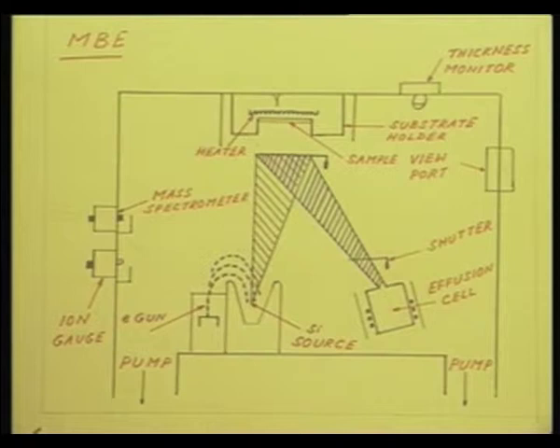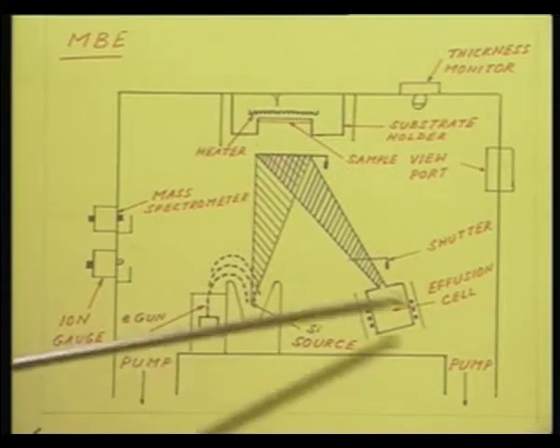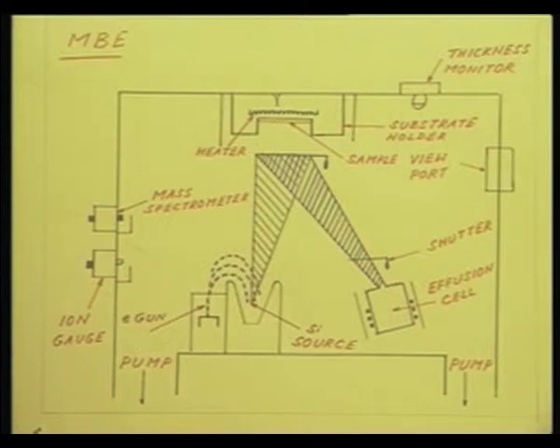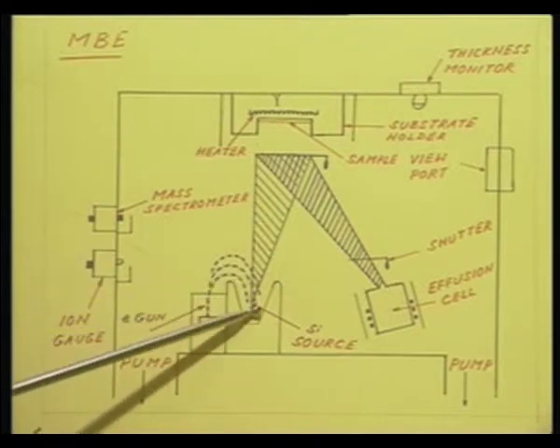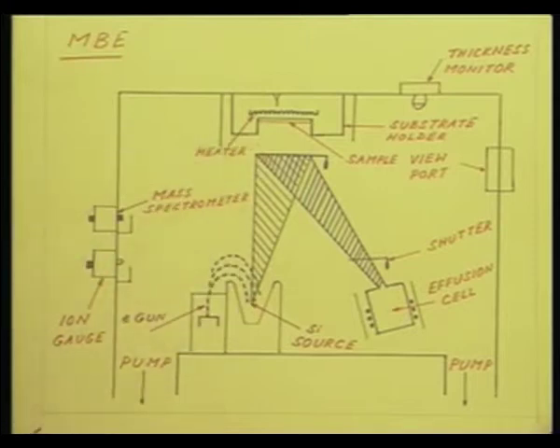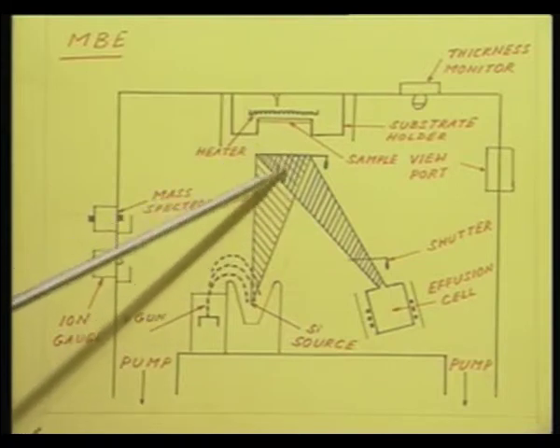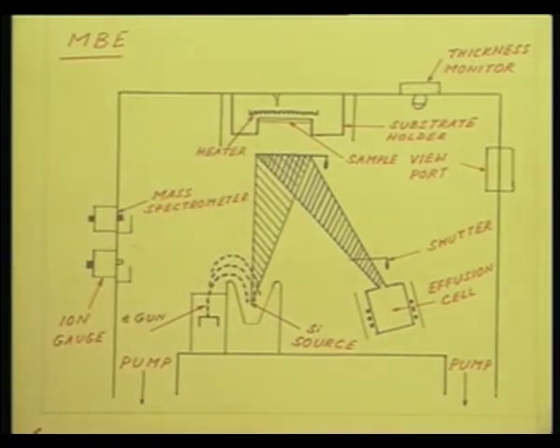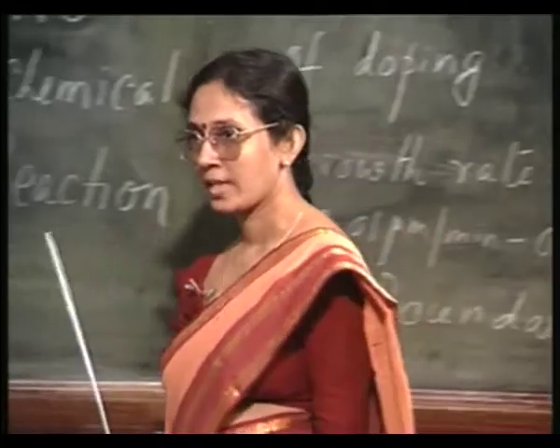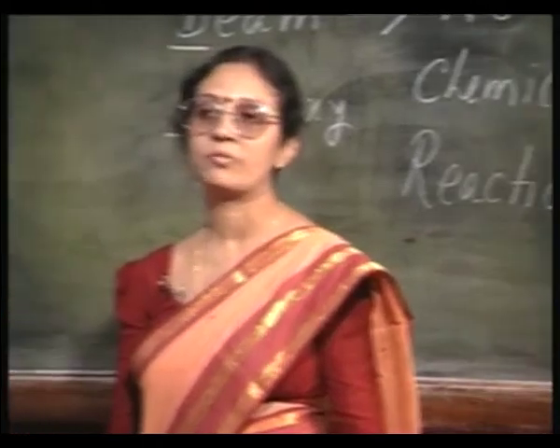So, essentially what is done is this: you pump down the system to the required vacuum level, and then you switch on the electron gun, the evaporated cone of silicon comes here. If you want to incorporate dopant, you heat the effusion cell, open the mechanical shutter, the dopants are also incorporated. So, this hatched region is actually where the silicon mixed with the dopants are available, and that goes and gets deposited, condenses on the relatively lower temperature substrate. Very simply said, but it is more difficult to achieve.